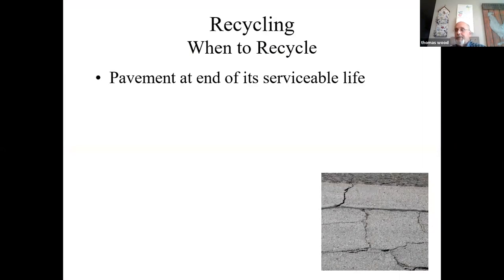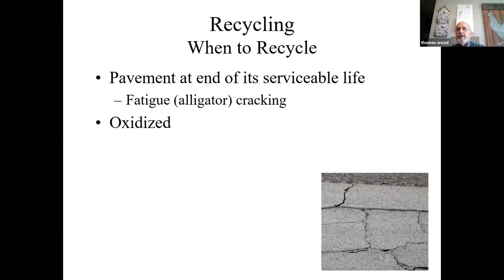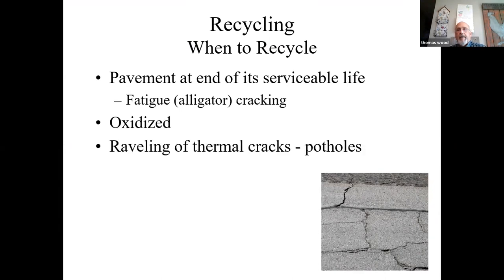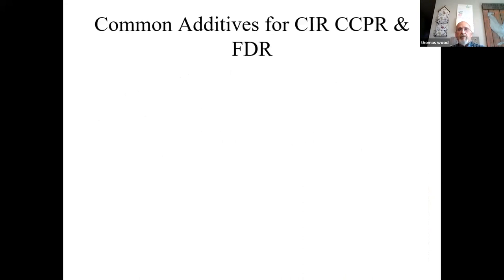So when are we going to recycle? Well, we're going to recycle at the pavement's end of its service life. We want to get as much bang for the buck as we can out of the pavement. Some of the things that drive it are fatigue cracking, alligator cracking, severe oxidation. And to me, severe oxidation doesn't drive it as much as the cracking, whether it's fatigue cracking or thermal cracking, and potholes. The other advantage of doing cold in place recycling is you can keep your elevation down, like I said, so your in slopes don't get so steep. And if you have any overhead, like bridges or anything that you've got to go under, you can maintain your clearance.